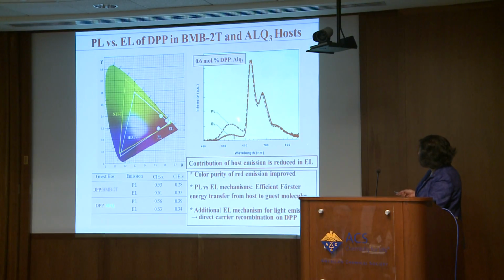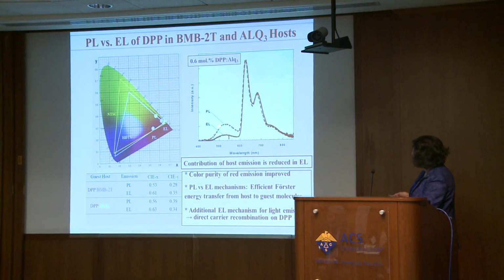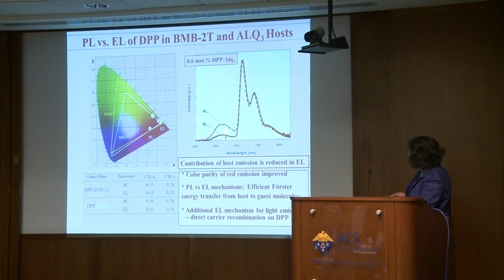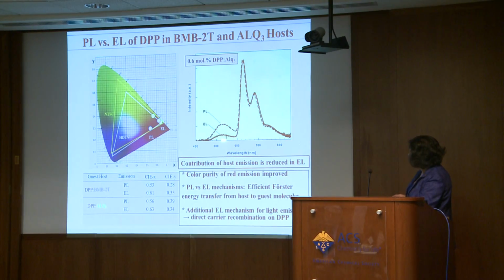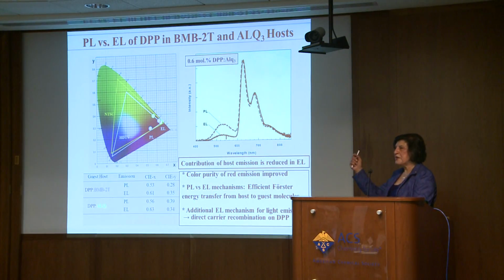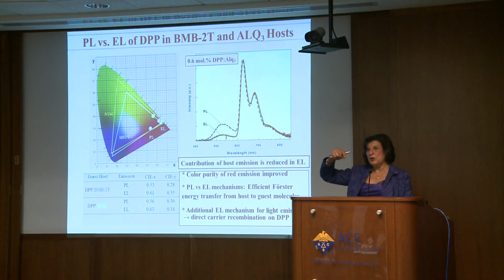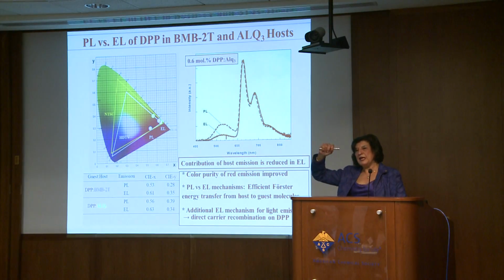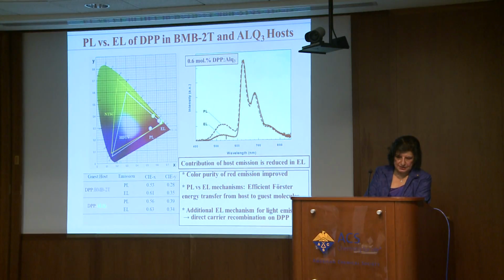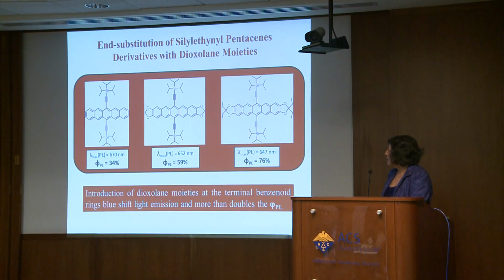If you compare here the fluorescence, the PL spectrum, and the electroluminescence, we see a difference in the host emission, which signals that there is another mechanism that we characterized, in which the electron and hole, rather than being recombined on the host and then energy transferred to the guest, are directly recombined on the guest. We also, in collaboration with John Anthony, developed another pentacene derivative with higher photoluminescence quantum yield.